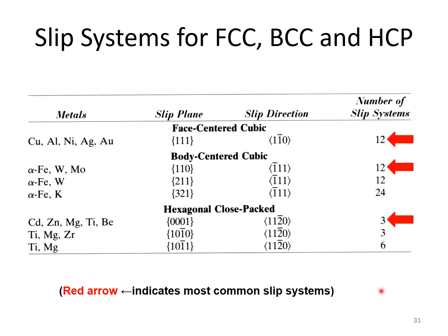So this slide just summarizes the number of slip systems that's possible, the number of distinct planes and directions on which you can slip in an FCC case. So there's lots of opportunities for shearing by dislocation slip in the FCC case. In the hexagonal system, this simple ball model glide, which is equivalent in the hexagonal case to that, you only have three possibilities on that plane, or three possibilities on the prism plane